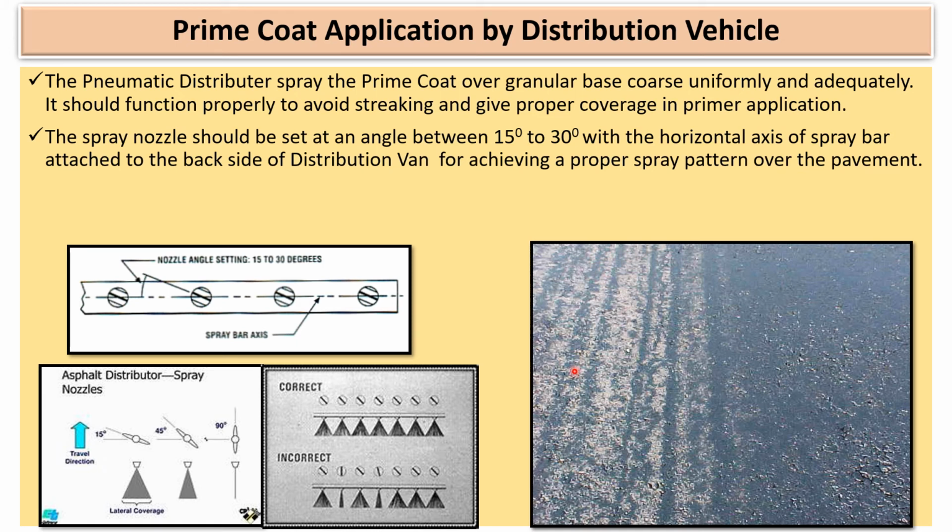over the pavement. The defects may be due to the improper functioning of all the nozzles in the spray bar, or insufficient bitumen emulsion in the tank, or clogging of one or two nozzles in the entire set, or early curing or setting of bitumen either inside the tank or over the base course early.